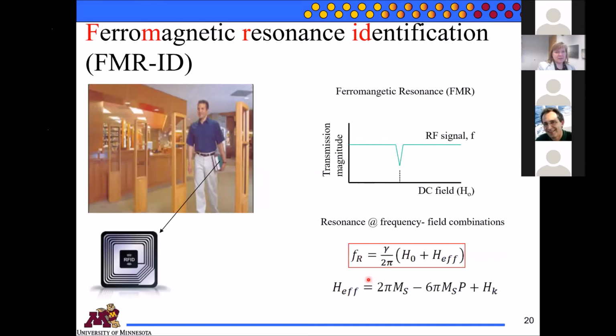I think I have another 6 or 7 minutes, so I might go a little more quickly through the FMRID that we're working on, because I assume this audience probably has a good idea of what FMR is. Ferromagnetic resonance is the idea that you could apply an RF signal, and if you have a DC field and you sweep that field, there's going to be a certain DC bias frequency combination that has absorption in the sample because you have a resonance of your moment. And that's something to be characterized by this well-known Kittel equation. And this also actually comes from Perrot's group when they first investigated nanowires for FMR.